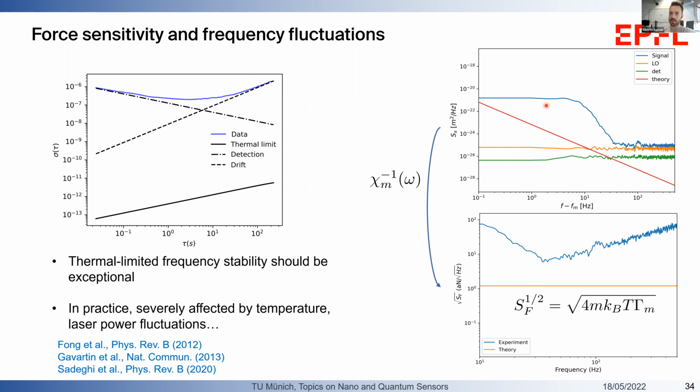You can see that the effective susceptibility in these measurements of the thermal displacement is much broader than the millihertz line width that is measured by ring down measurements, and correspondingly, we couldn't resolve the force sensitivity predicted by the fluctuation dissipation theorem, the thermodynamic limit of force sensing.